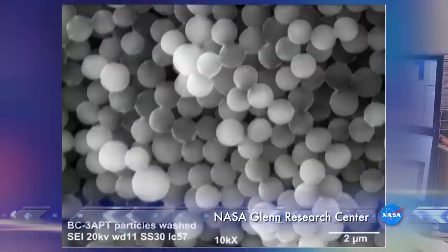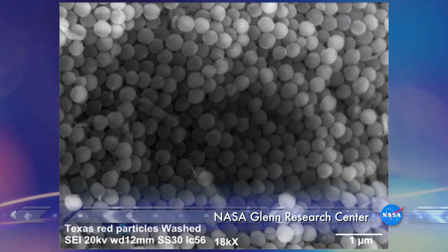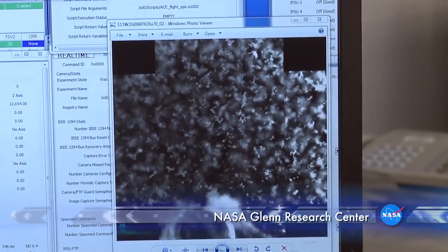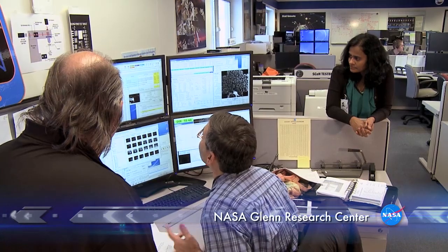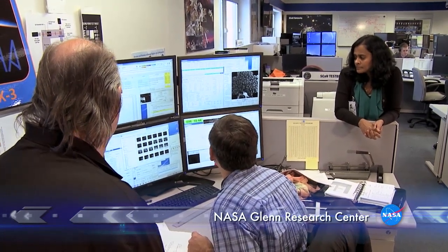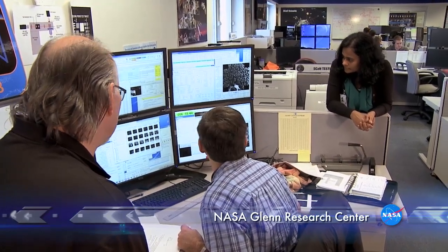One of the key issues that we run into when we perform these experiments on the ground is that gravity forces the crystallization to happen on a 2-dimensional surface, which means that we only can get one type of crystal structure. And we know that that crystal structure is based only on the large particles. It does not incorporate the small particles. By doing these experiments in microgravity, we're hoping to be able to drive the crystallization of both the large and small particles simultaneously so that we can incorporate both particles into the ultimate structure.